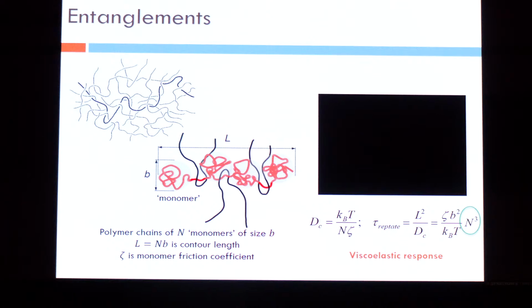And so if I take one of these polymer molecules and stretch it by applying a shear or by stretching it and then leave it, then the polymer has to relax back, because in an unsheared case, the equilibrium state of the molecule is to relax back into a more relaxed configuration. So how does it go from a stretched state or an oriented state into a relaxed state? And the way it does that is to escape through these tubes by a snake-like motion. Okay? That's the idea behind how these polymer molecules relax in an entanglement network.